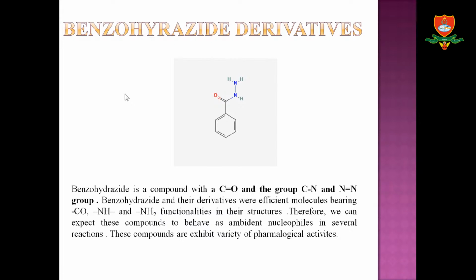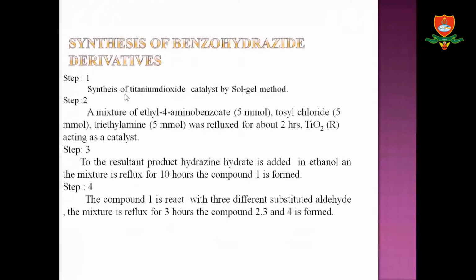A benzohydrazide compound contains a carbonyl group, CN group, and NN double bond group. Because of the presence of these groups, the molecule exhibits a variety of pharmacological activities, and also it behaves as an ambident nucleophile in several reactions. The synthesis of benzohydrazide derivatives involves four steps. In first step, a titanium dioxide catalyst is synthesized by Sol-gel method, and in second step, a substituted sulfonamide is synthesized. In step 3, the synthesized product is reacted with the hydrazine hydrate to form a hydrazine substituted product. And in the fourth step, the synthesized compound 2, 3, and 4 is formed.